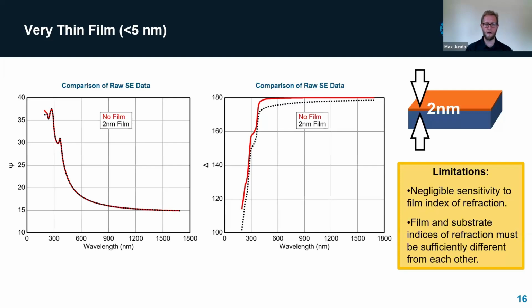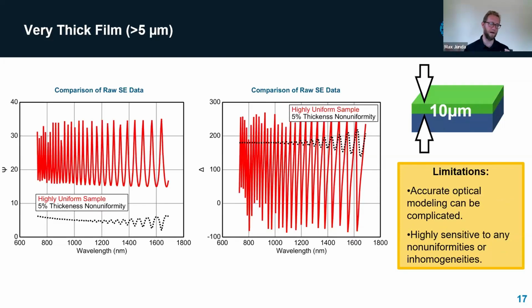All right, so on the next slide, we're going to talk about very thick films. So here on the other end of the spectrum, the wiggles are bunched very tightly together. And I'm showing an example here of simulating data for 2 different cases. These are the exact same film. It's 10 microns thick. But in the case of the red data, we've simulated the case where the film is perfectly homogeneous. It's very uniform. It's a nice high quality film where there are no differences from top to bottom or left to right. And then in the case of the black dotted line, exactly the same thing, but we've just added 5% thickness non-uniformity, meaning that in the place we measured, the thickness of the film is actually varying a little bit. It's not perfectly flat.